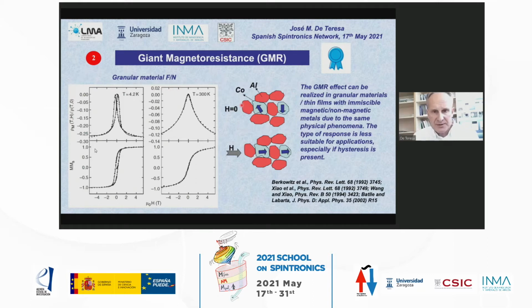Okay, from the experimental perspective, we can also say that a similar effect can be obtained in a simpler material. In this case, a granular material. So you can prepare a granular material with ferromagnetic grains and with non-ferromagnetic metallic grains, such as this cobalt aluminum granular material. So at zero magnetic field, you will have magnetization, which is in principle randomly distributed. And when you apply the magnetic field, you have parallel alignment of the magnetization of the grains. So you will obtain something similar to the giant magnetoresistance effect we have observed in multilayers.